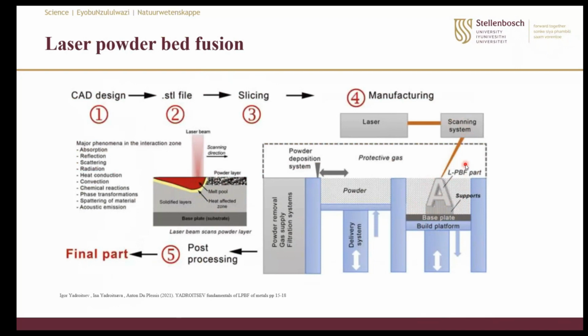The disadvantage with this method is that during printing, several things can occur. One of them is that as the laser is forming the layers, weak bonds may form within or between the layers, and that is a defect which we call lack of fusion porosity. Another one can be that a depression well filled with vapor may collapse and form holes with a keyhole shape.